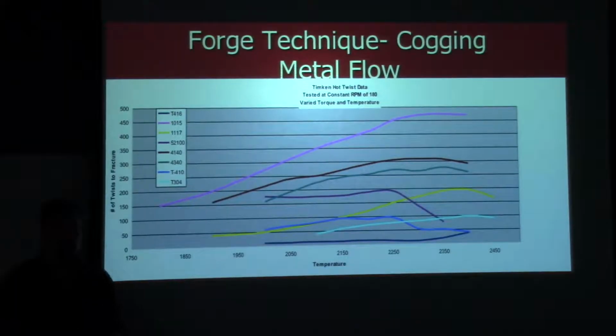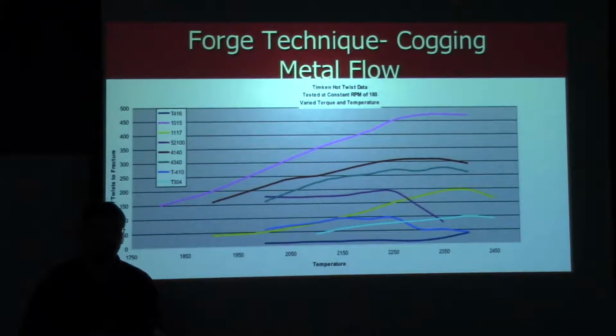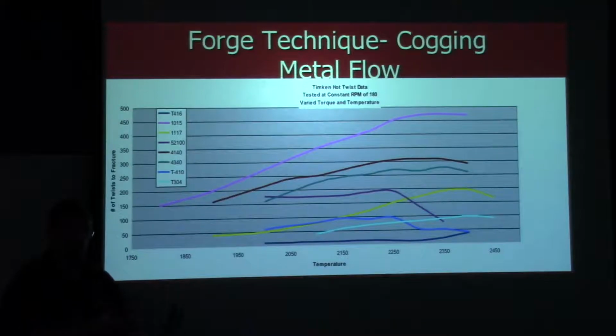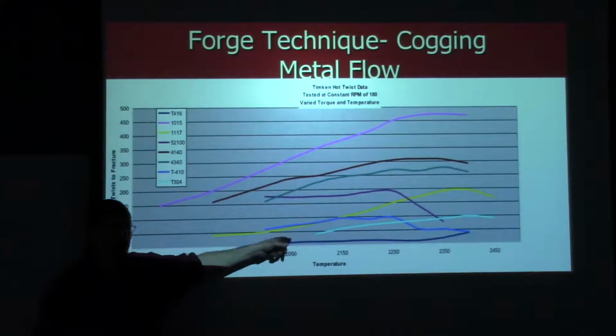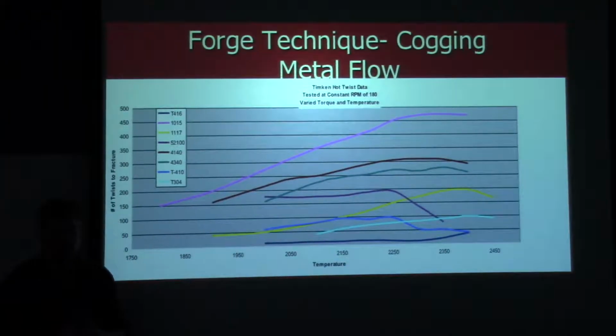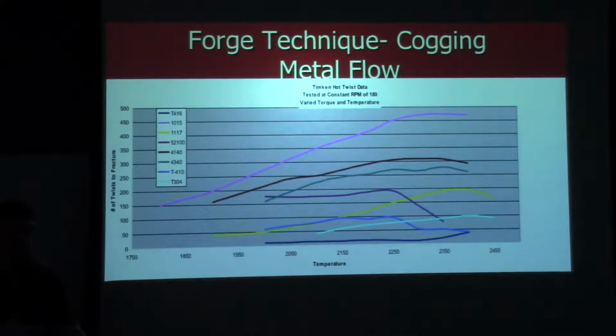But manganese sulfides are not steel. They're much softer, much weaker. So if you have a high concentration of manganese sulfides and you're doing some plastic deformation, that's going to potentially serve as an initiation site for a rupture during the deformation process. And that's what's being shown here, that's what's happening with those sulfides. And we observe this at work. When we forge these grades, we have to use extra care, because if we don't, we'll actually cause internal tears and ruptures